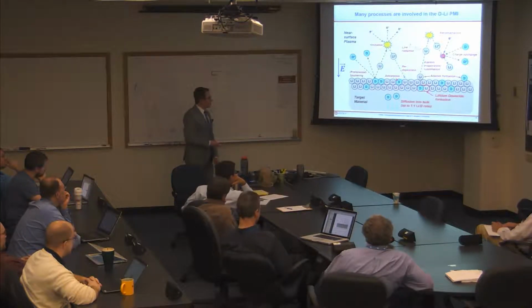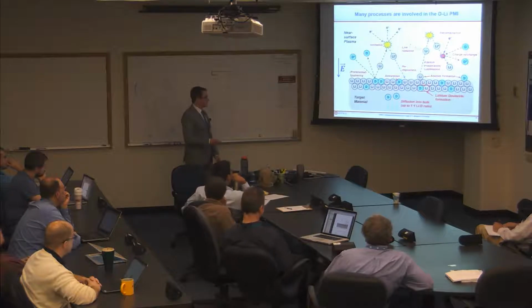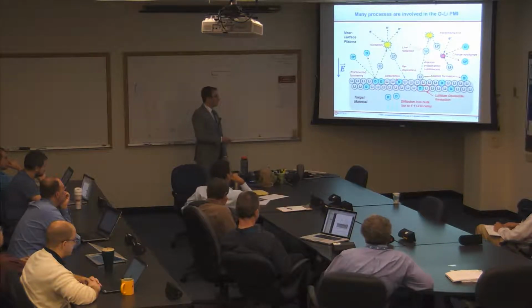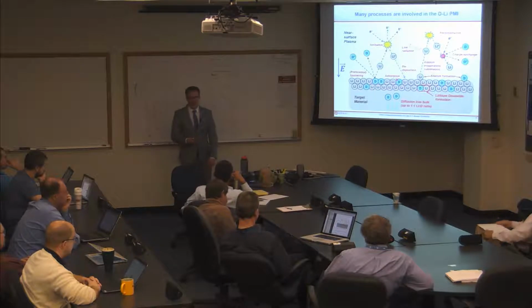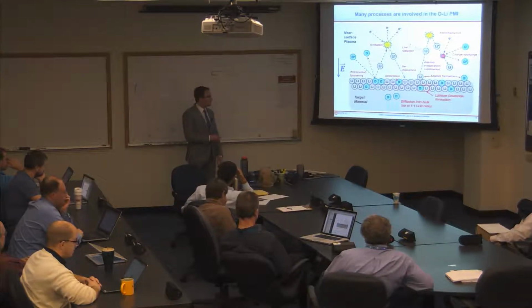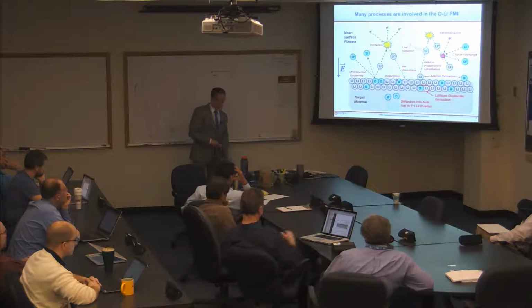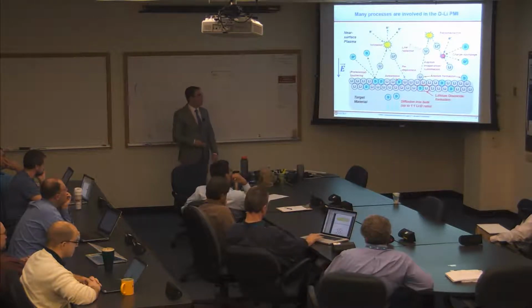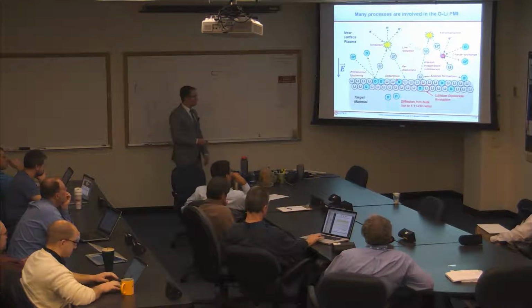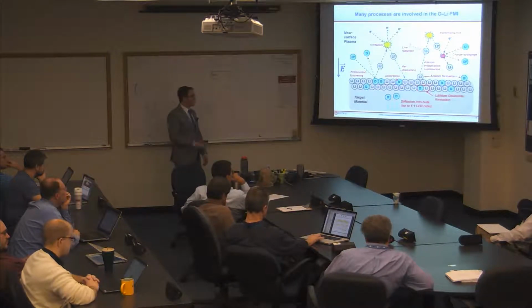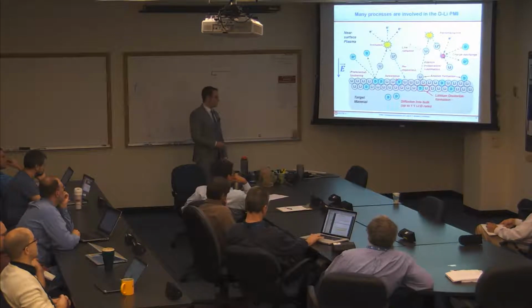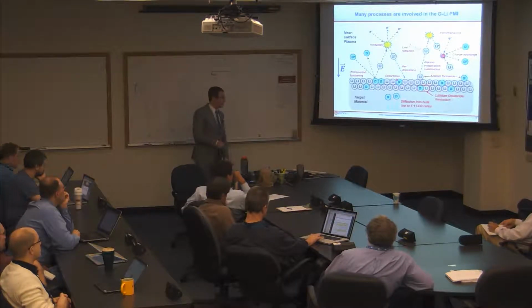And then in the material, you can have a number of things going on. You can have chemistry effects, such as adsorption, which is basically when an atom chemically binds to a surface, or either chemically or just is physically implanted into a surface. You can have formation of lithium deuteride. Because lithium is an alkali metal, it reacts very readily with hydrogen, and so it forms the lithium deuteride compound. And then you can also have diffusion of these deuterium atoms deep into the bulk of the lithium layer. And it's been observed in experiments that this will occur up to a 1-to-1 lithium-deuterium ratio.